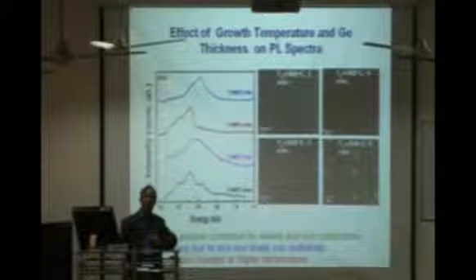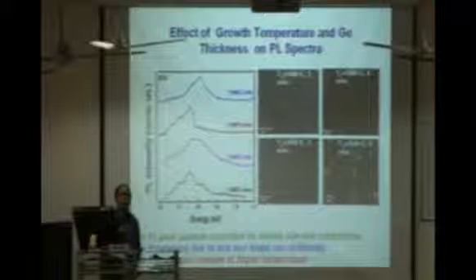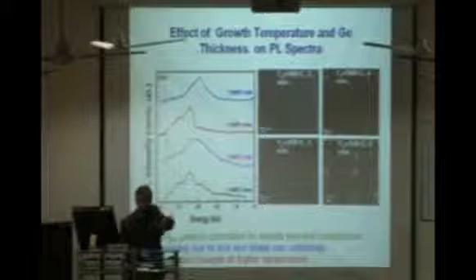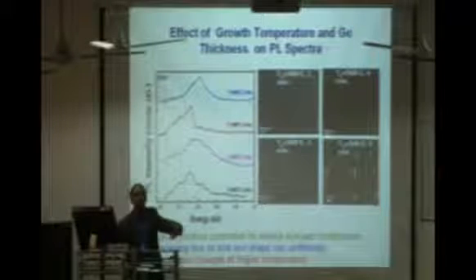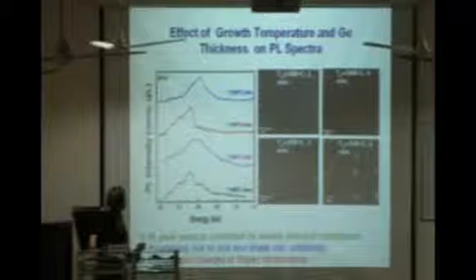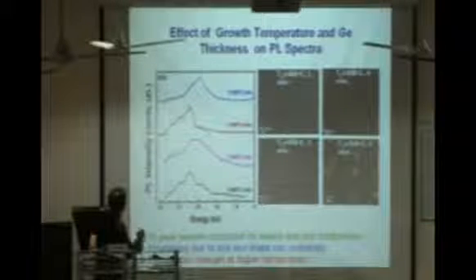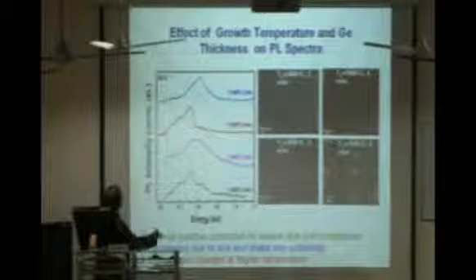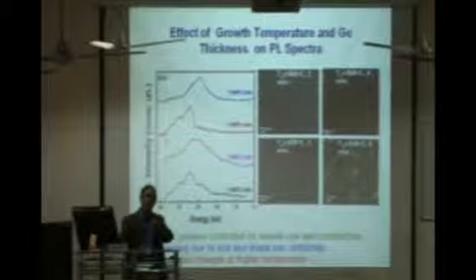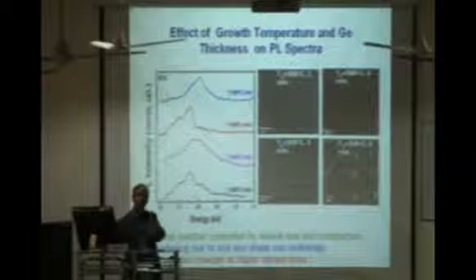Because of the formation of excitons, ultimately the excitons decay and recombine and give what is called photoluminescence. In fact, we excite these quantum dots with lasers, and finally you see their recombination mechanism by an experiment called photoluminescence. This photoluminescence experiment is done for these germanium quantum dots, normally at a low temperature like 10 Kelvin, and we can get very good emissions. What we want to show is that this emission energy shifts as a function of the size of the material, what is called the quantum size effect. That is one direct proof that if you get a size dependent shift of the luminescence or the optical absorption or emission peak, you know that this material has entered the so-called quantum region.